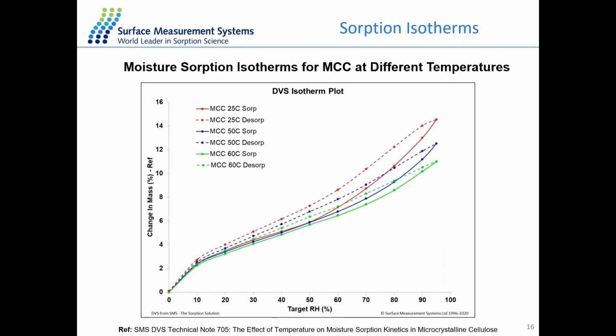And another observation is about the hysteresis gap between the sorption and desorption isotherm. So here is just a comparison of the isotherms at different temperatures. The red line is for 25 degrees, the blue line is for 50 degrees, and the green line is for 60 degrees. As the temperature increases, the water molecule will move more freely out of the bulk structure, which results in a smaller hysteresis gap in this superimposed plot, and also an increase in the diffusion constant in the previous slide, because higher temperature has more energy input for the water molecule to go from the bulk to the surface for the desorption.